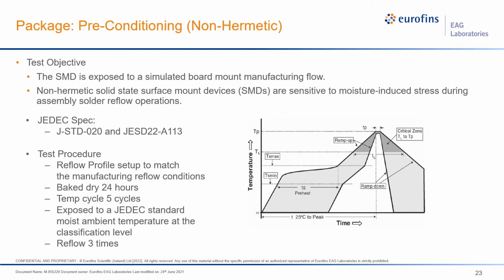The diagram on the right side of the slide shows a solder reflow temperature profile over time. Now, each device has its own specification about how it's to be attached to a PCBA. So there's a specific solder reflow. During preconditioning, this solder reflow is duplicated to match the device specification. Following the preconditioning, the device must be electrically tested to verify that it still meets all its specifications, it's still fully functional. And you may refer to the JEDEC spec for more details on preconditioning and moisture soak.